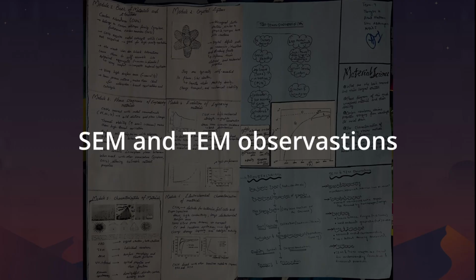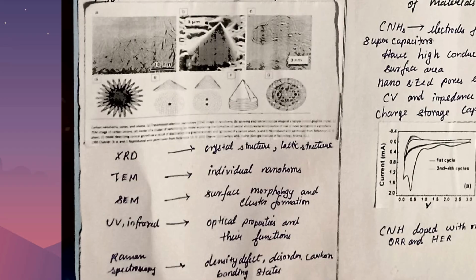Scanning electron microscope and transmission electron microscope observations. From the SEM and TEM observations, we can see the aggregated morphology where we see how the nanohorns self-assemble into spherical dahlia-like clusters which contributes to their high surface area and porosity. Each nanohorn exhibits a conical shape with a distinct tip formed by non-hexagonal rings that is characteristic of their formation. HRTEM reveals clear lattice fringes confirming their high degree of graphitization and structural order. The images suggest that as synthesized, the nanohorns are relatively free of metal contaminants and have minimal defects, beneficial for various applications such as catalysis, gas storage, and drug delivery.